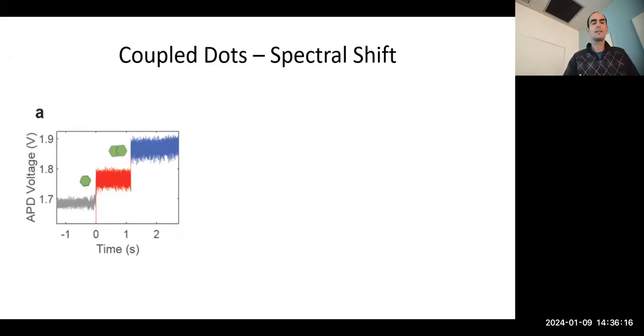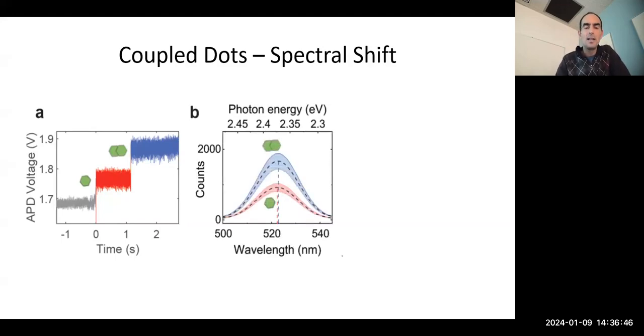What was more interesting and somewhat unexpected - not typical for our experiments, usually you just trap one particle, since in a stable colloidal system particles by definition are not aggregating - is that with these perovskite quantum dots, we usually saw another one join in the trap. So you get not just a single jump, but a second jump, where two quantum dots are trapped at the same time.